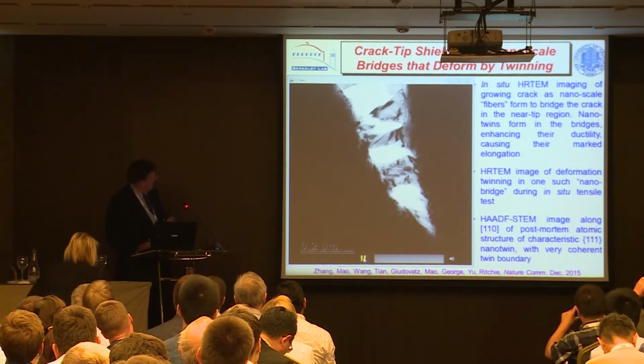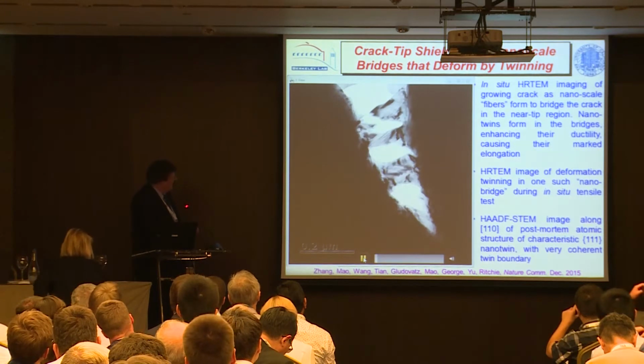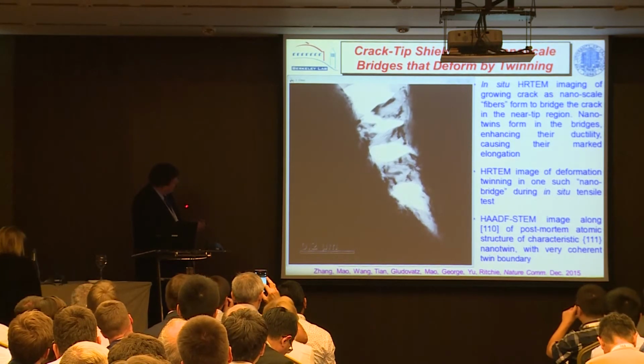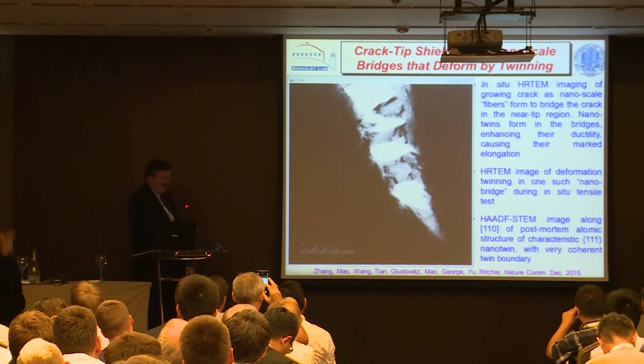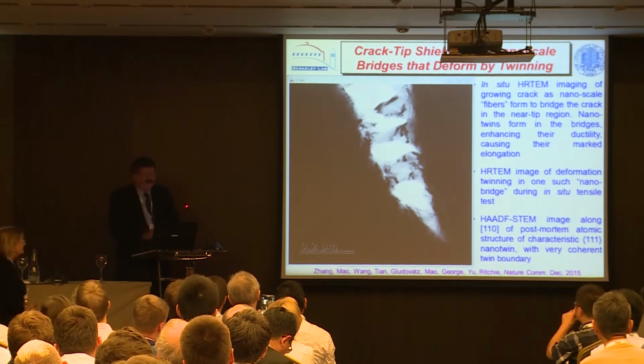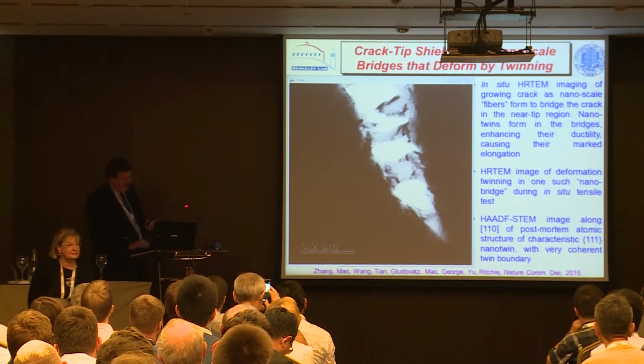If you look at the crack tip, you see these little nanoscale bridges that form across the crack, and these are actually twinning as well. Now this could be an artifact, but it's still very, very interesting.